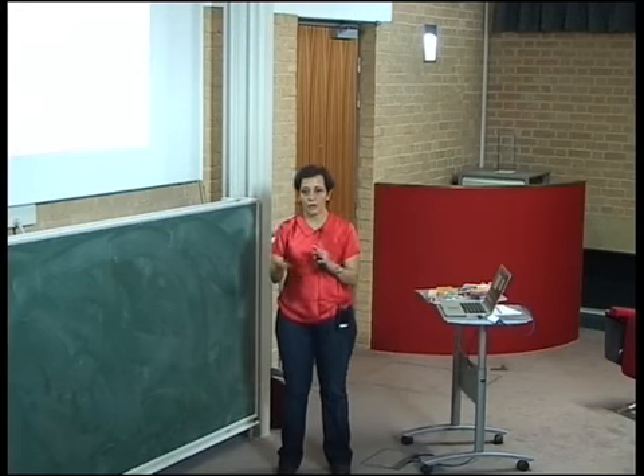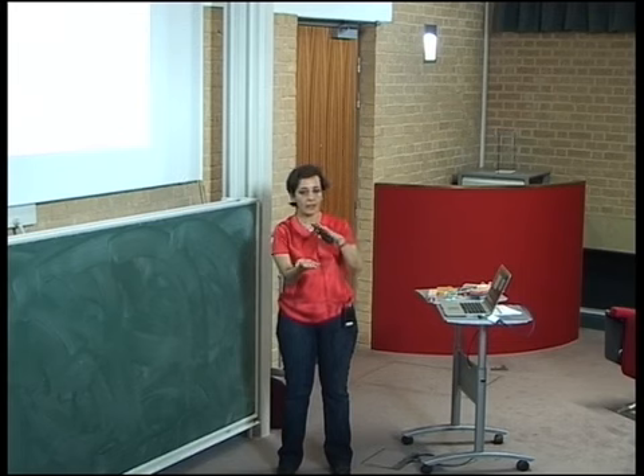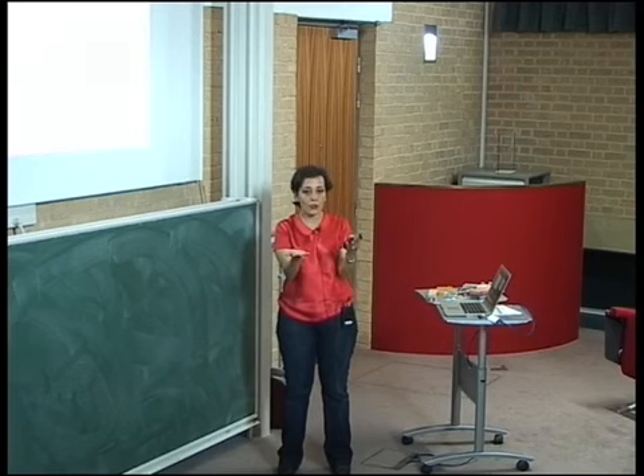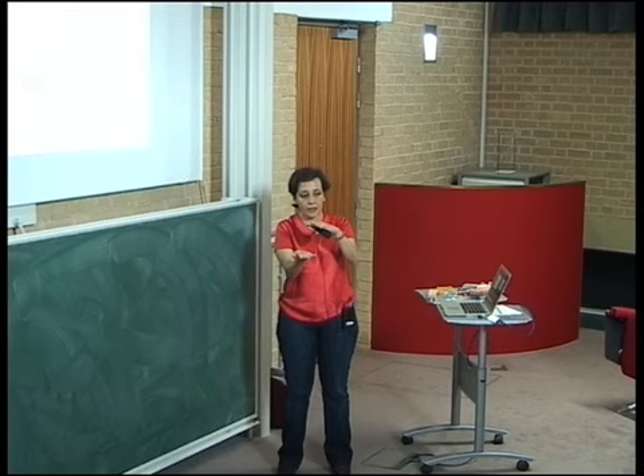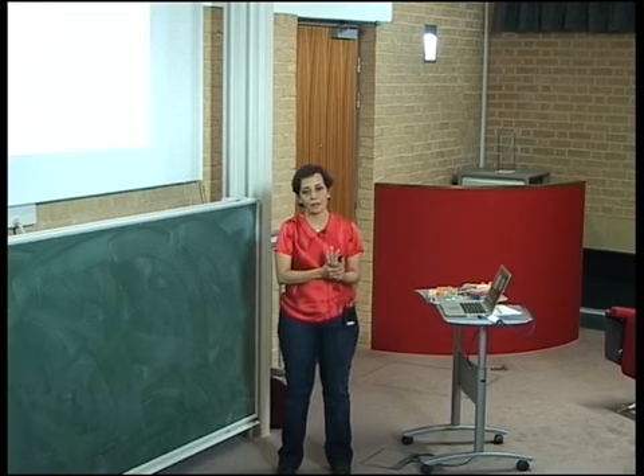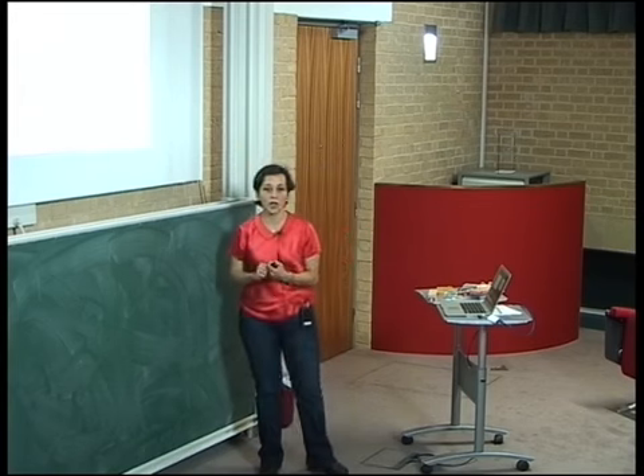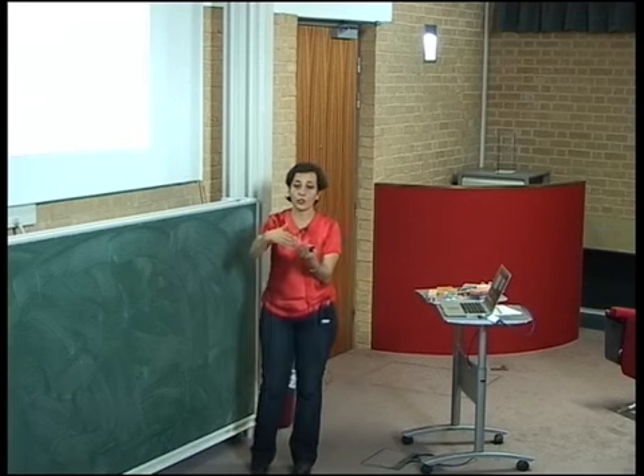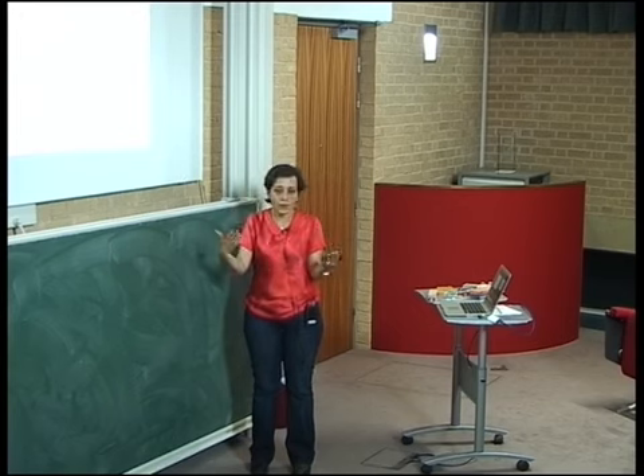You said that there are elasticity properties. Is this on long timescales, or is it just viscoelastic at initial time before it starts to restructure? Actually, we do see an elastic response using shear rates, so we deform the system at fixed shear rate, right? And then you measure a modulus, and this modulus does not significantly change in a relatively wide range of shear rates, which are of the order of the relaxation time of the system. So yes. I can take the stress and plot it as a function of the deformation and get a shear modulus.